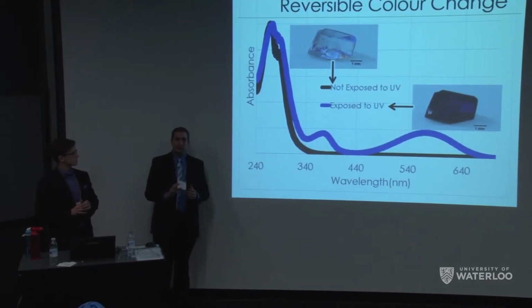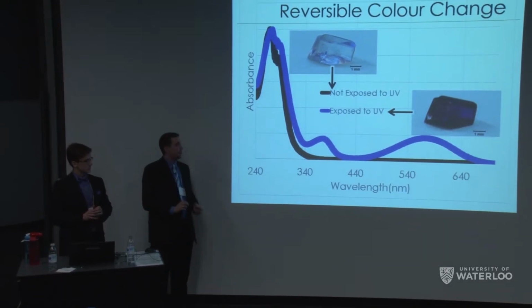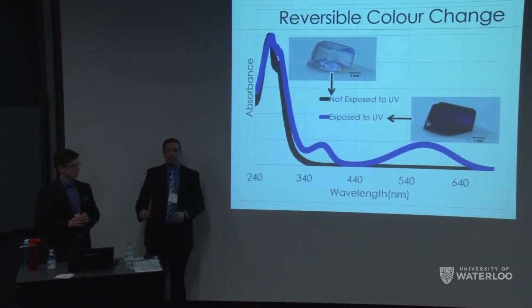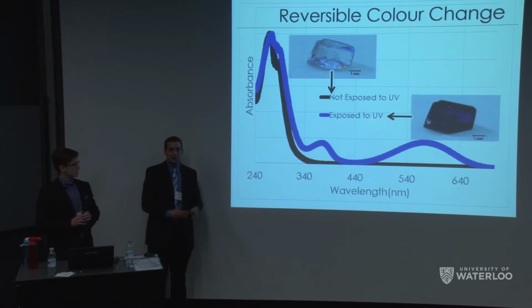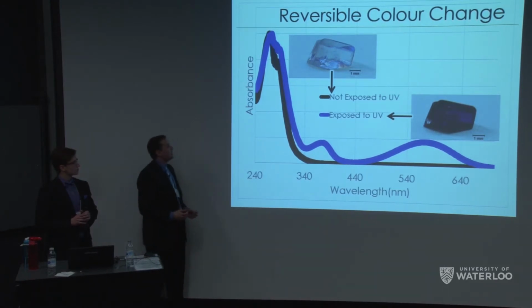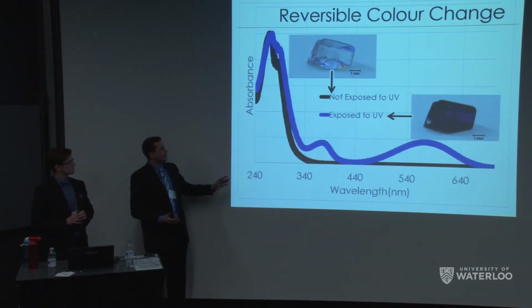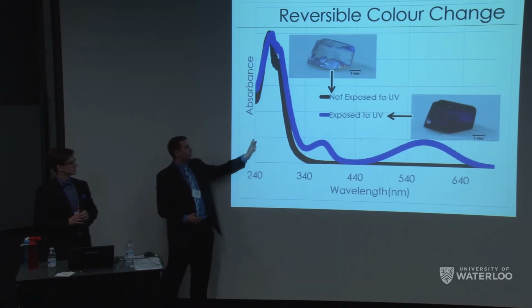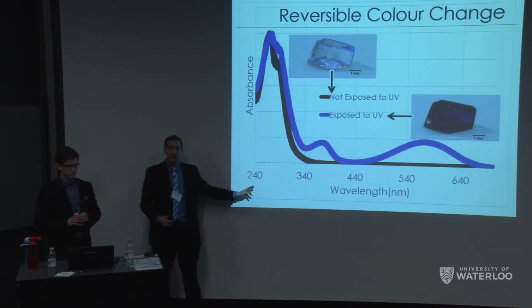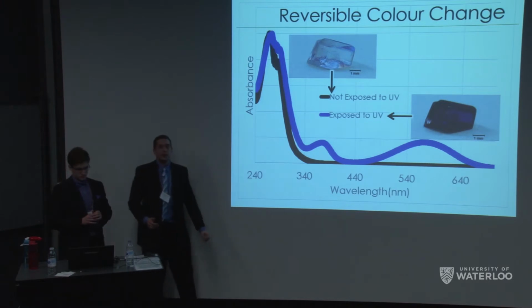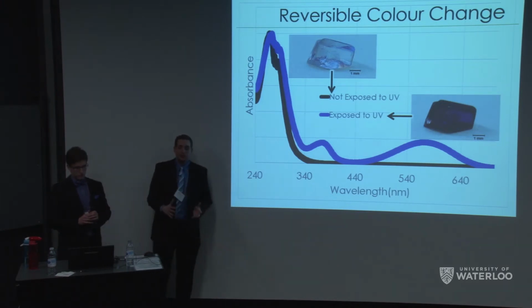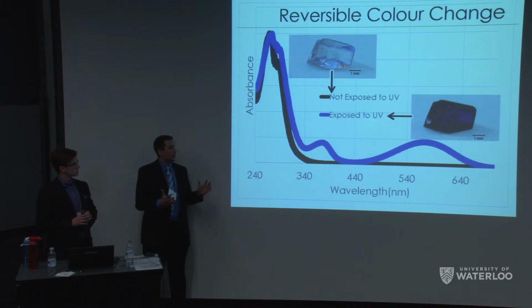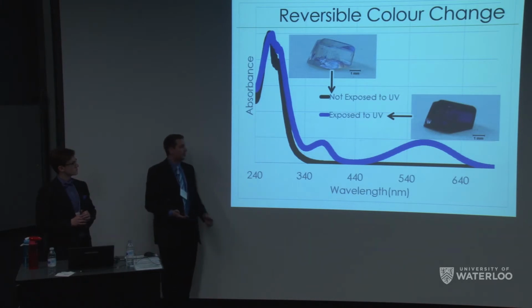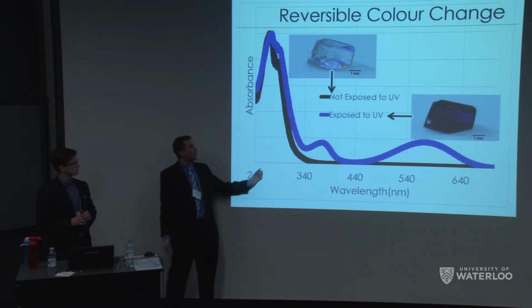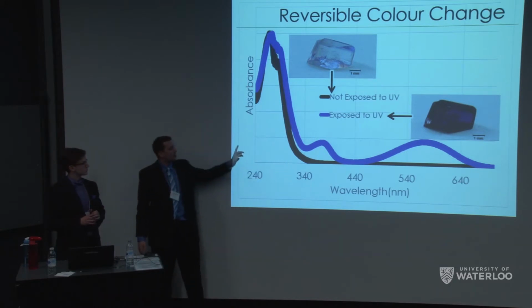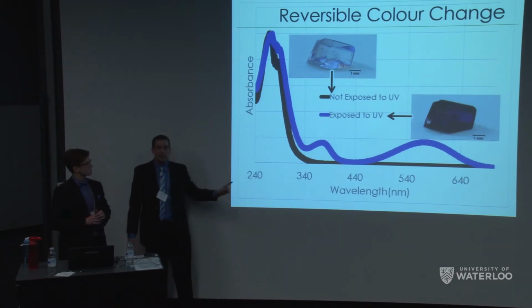They are actually the exact same sample. The difference between them is the purple curve has been exposed to UV light for about 30 seconds, and then its absorbance measured. If you consider the black curve here, which is not exposed to UV light, it has a large absorption in the UV range, from about 240 to 340. Upon exposure to UV light, this absorbance interacts with the molecule and allows it to conformationally change, and if it's exposed for even only up to 30 seconds, it will shift to what the purple curve looks like, where you see a change in the absorbance and now have visible light absorbance.